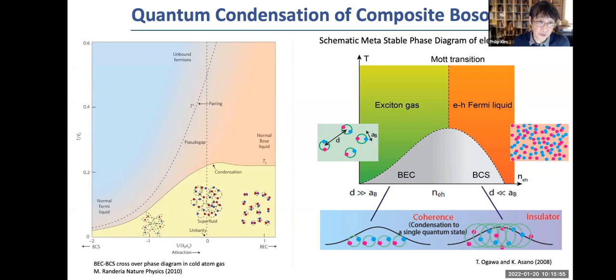But at the other limit, if you pump in more excitons, such that the distance between the excitons is really comparable to the size of the exciton, the constituent electron and hole in the exciton start to screen each other and make the binding energy weak. So at high temperature, they can just unbind into an electron-hole plasma. At lower temperature, that electron-hole plasma can be degenerate and eventually can condense into superconducting-like condensation, right? So as you see in this example, by controlling the exciton density, you may be able to see the so-called exciton BEC to BCS type of condensation. While this has been a really beautiful